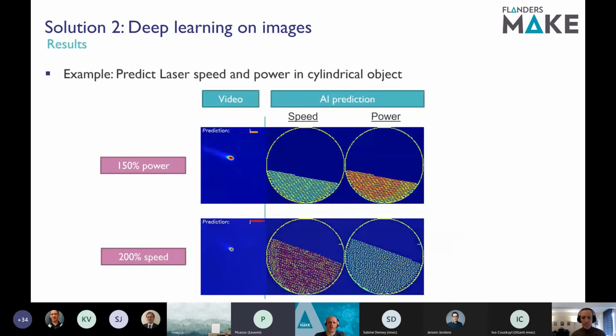So after training, if you want to test it, here you see some results. Here we changed the power of the print in the first experiment on the top. On the left-hand side, you see the recorded video. So this is the raw video. And on the right-hand side, you see the predictions by the AI module. And what we see, if we increase the power, is that the AI module predicts that the power is higher than optimal, and this is indicated by the orange color, but the speed is still optimal, indicated by the green color. So if we use this as input in the controller, we know that we need to change the power and keep the speed constant.